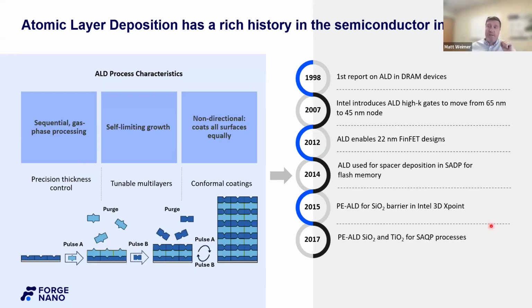But I wanted to show a little bit of history of ALD in the silicon microelectronics field and really point out what happened in 2007. As I alluded to earlier, this is when ALD really had its moment in the sun. Intel was struggling to reduce the node size from 65 to 45 nanometers with their existing dielectric technologies. So they adopted ALD of hafnium dioxide as their high-k metal gate dielectric. It gave a high quality film, and at this point in history, Intel was the standard for manufacturing in the world. So for Intel to say ALD is a high volume manufacturing technology, everybody else agreed. That was really when ALD became a known commodity, as it were.